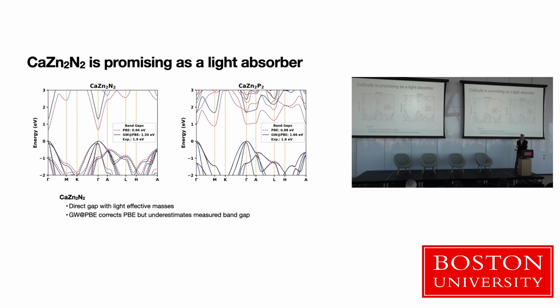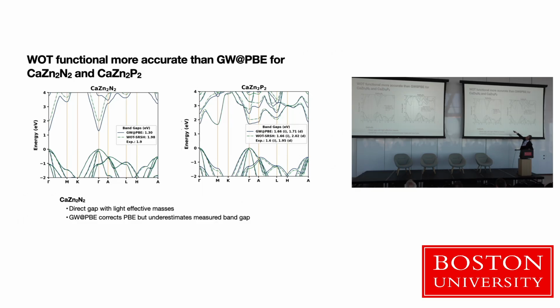This isn't published, but you can see for the calcium zinc nitride material on the left, it's a direct gap system. The phosphide is indirect, just slightly, and it has very low effective masses and a reasonably low band gap. Interestingly, if you look at the fine print here, GW does not quite predict the experimental gap very well, but it does improve. The WOT functional does a lot better with respect to the experiment. So these more challenging one-shot GW calculations aren't as effective for these systems.